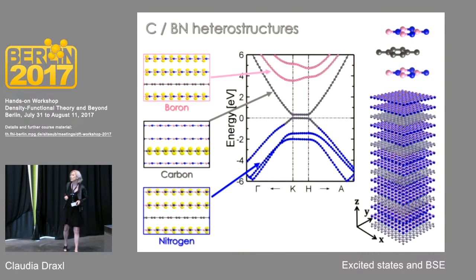And this you can realize when looking at the band structure. Now the color code tells us what the character of the bands is. So the gray dots here reflect the fact that the low energy range is dominated by graphene. This is actually what we expect, of course. But it also indicates the opening of the gap, which is of the order of 0.3, 0.4 electron volts,